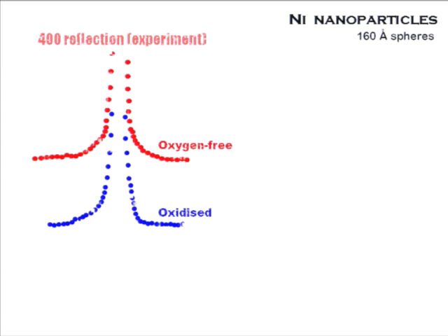And what we noticed at the time was that the peak shapes of the non-oxidized, as-prepared nickel particles looked quite all right, nothing unusual. But when we oxidized them by several atomic percent of oxygen, they started to look like this. This is obviously just part of one of the peaks, but all peaks looked pretty much the same.